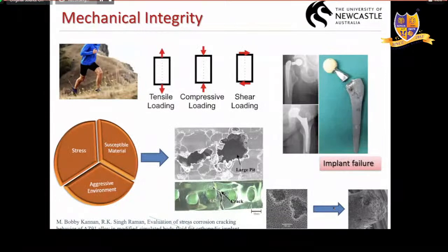Quickly, I want to touch upon one other topic, the mechanical integrity. It's very critical to look into the mechanical integrity because we are talking about orthopedic applications. The implants undergo various modes of stresses, and when the stress is combined with a susceptible material, they can cause cracking. Particularly, as I showed before, when there is pitting, this can cause failure. Even permanent implants can fail, let alone these biodegradable implants.